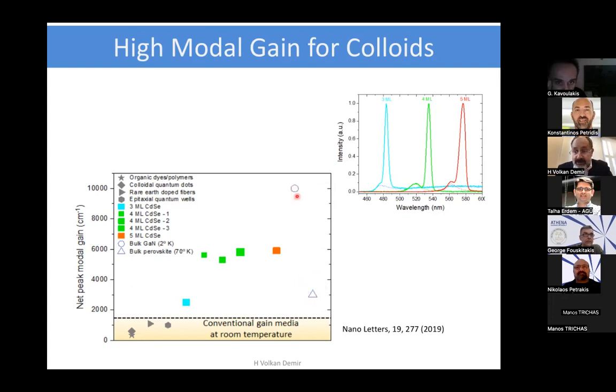And to make it a fair comparison, these are the best numbers we were able to find in the literature. This is bulk gallium nitride at cryogenic temperature, 2 Kelvin. And this is also another very promising material system we have been exploring ourselves too, perovskite. This is bulk perovskite, again, at reduced temperature. So this level of performance at room temperature with no active cooling actually looks very exciting.